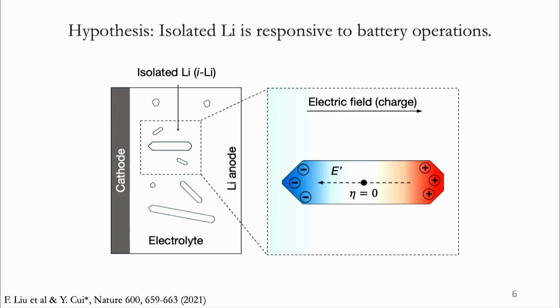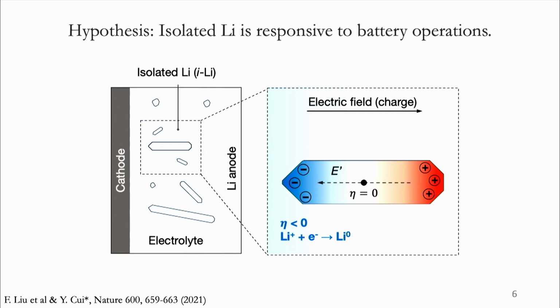On one side, it will have a large accumulation of negative charge, and on the other side, it will have an accumulation of positive charge or electron holes. But this accumulation of positive or negative charge will disturb the equilibrium state at this interface. For example, the accumulation of negative charge will drive the lithium ions in the electrolyte to be deposited onto this filament. And on the reverse side, the accumulation of positive charge will drive the lithium metal to dissolve into the